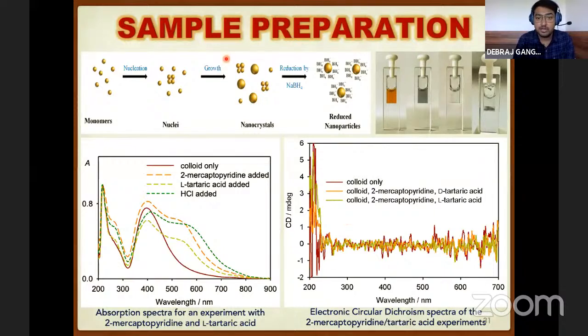First of all, we prepared the silver nanoparticles in colloidal form, which were used for this study. This is the absorption spectrum of the colloid only. When we used 2-mercaptopyridine, the linker molecule, for which we will observe the SERS, it broadened. There was a broadening in the absorption spectra, and we have used L-tartaric acid in very small amount, about 5 mole%, and it doesn't change the absorption pattern. So we have used HCl for aggregation of the colloids so that we get better SERS enhancement. After that, it looks like such a broadened absorption peak.